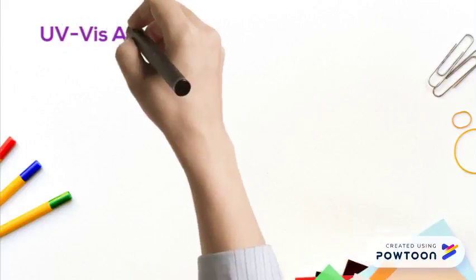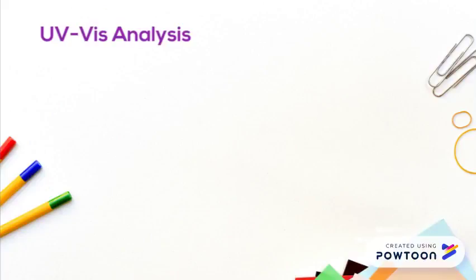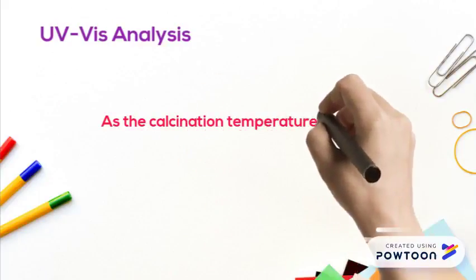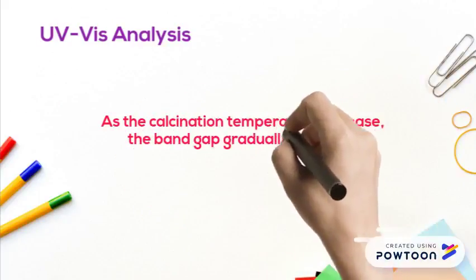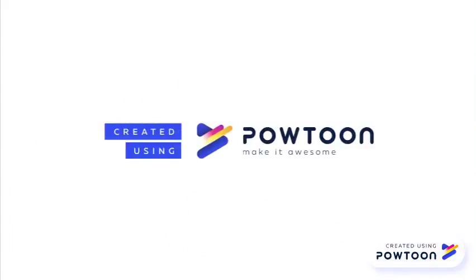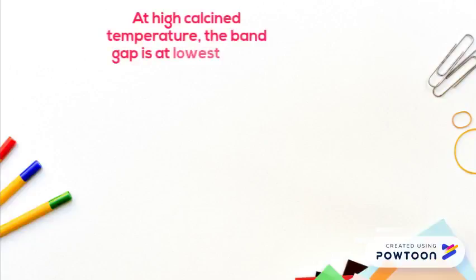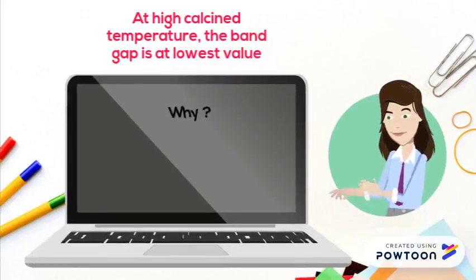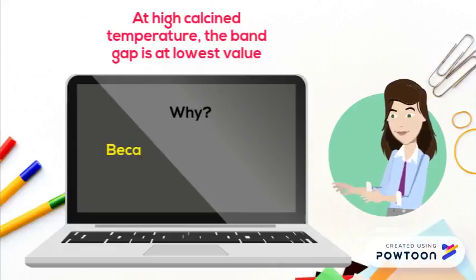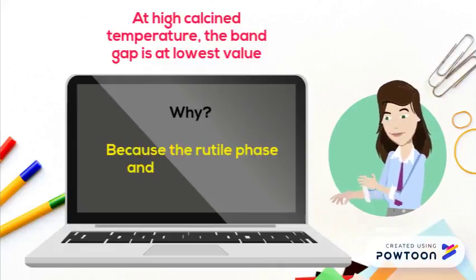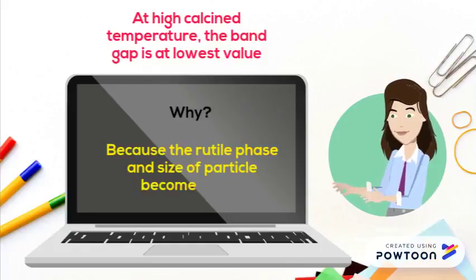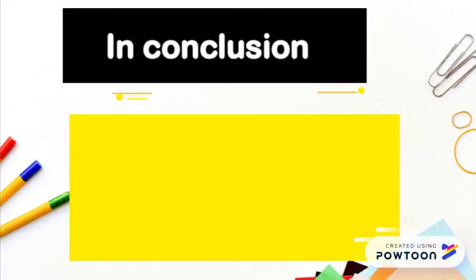For the UV-Vis analysis, we can see that as the calcination temperature increases, the band gap gradually decreased. At the high calcination temperature, which is 600 degrees Celsius, the band gap was at the lowest value, which is 3.0 electron volt, because of the rutile phase and the particles becoming bigger.